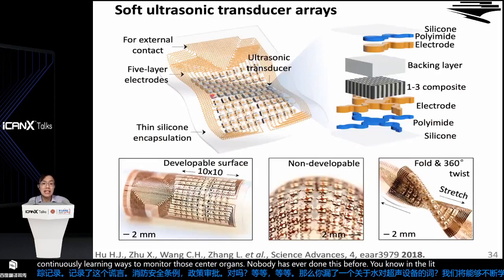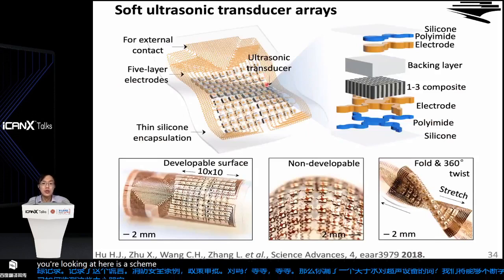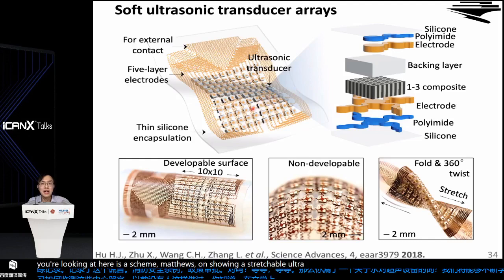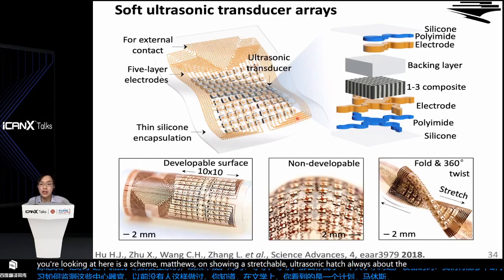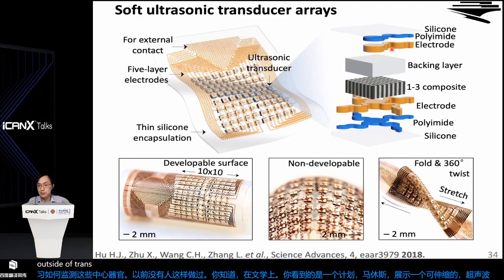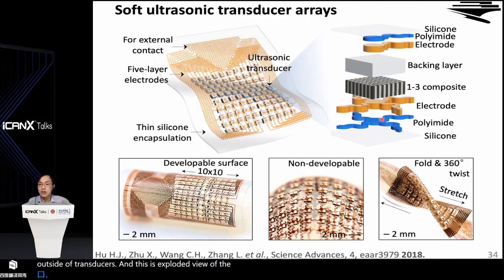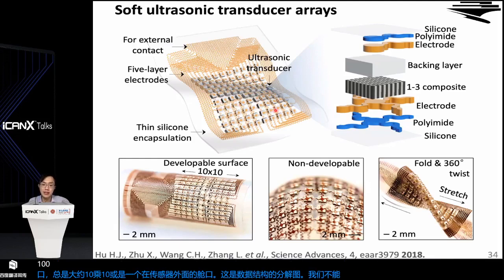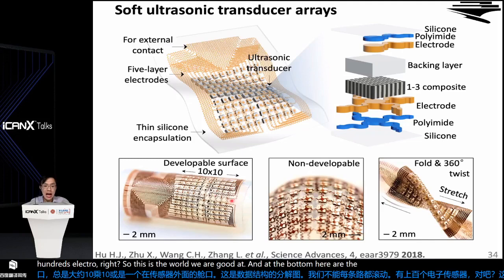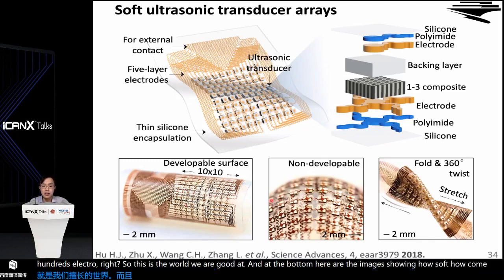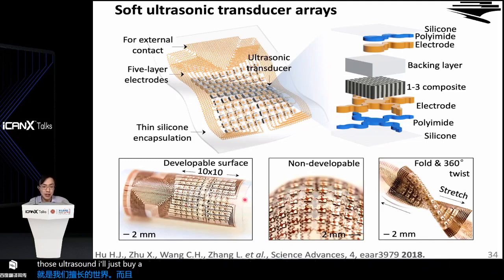So what you're looking at here is a schematic design showing a stretchable ultrasonic patch with about a 10 by 10 array of those ultrasonic transducers. And this is an exploded view of the layer structures. And we control each one of these transducers with over 100 electrodes, right? So this is what we are good at. And at the bottom here are the images showing how soft, how compliant those ultrasound devices are. It can be bendable, it can be stretchable, it can be stretchable with all kinds of mixed modes of deformation.